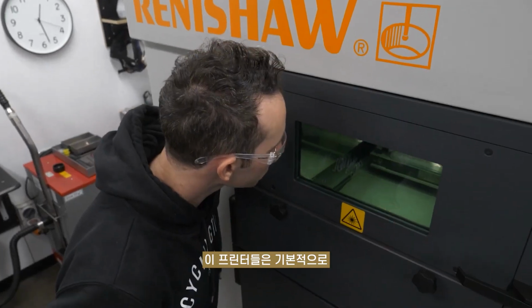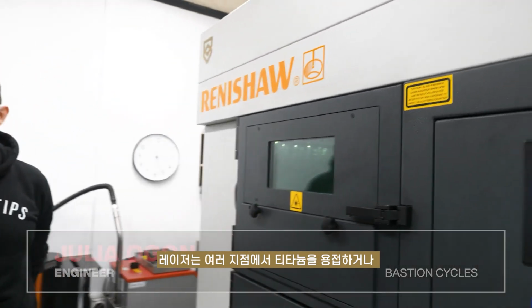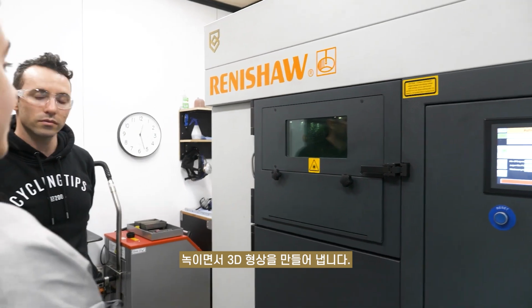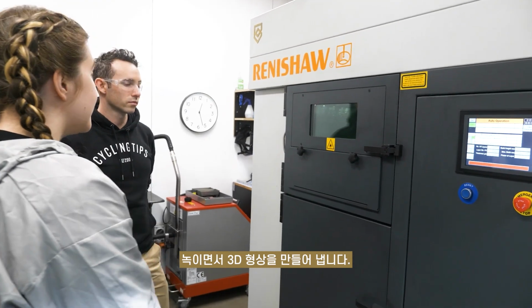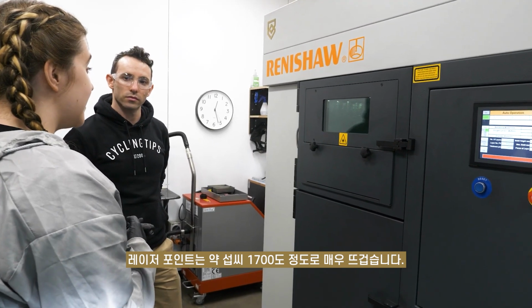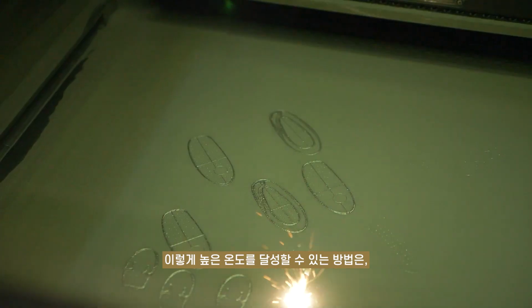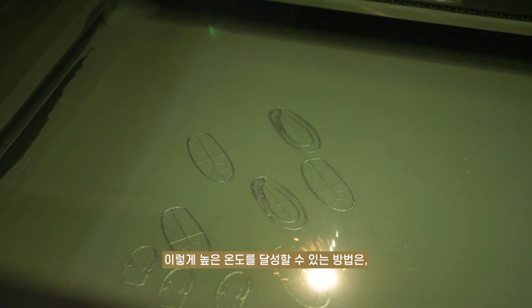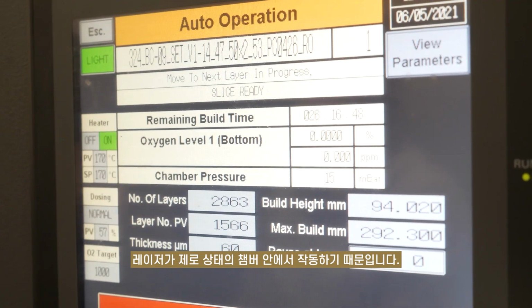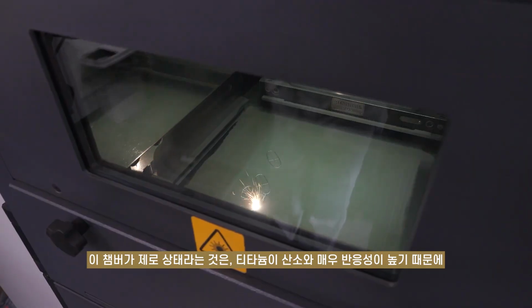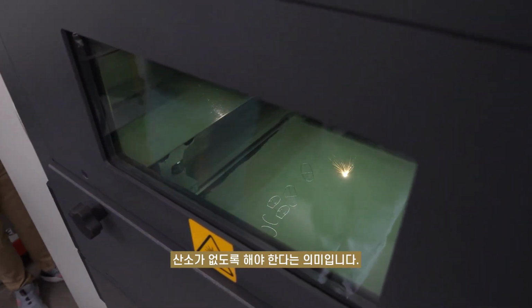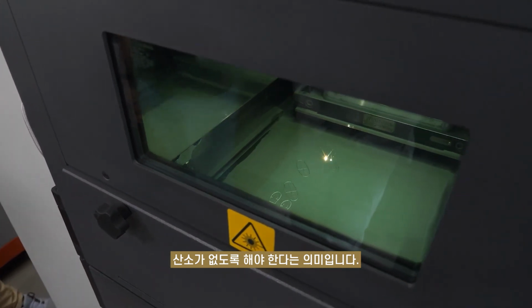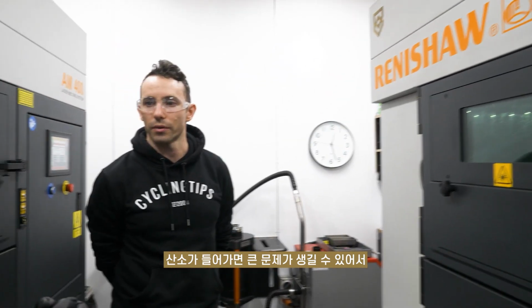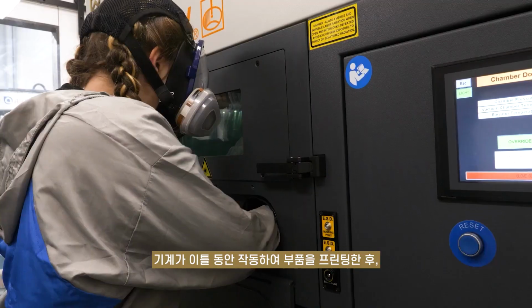So these printers essentially run off a really strong laser. The laser essentially in very minute points is welding or melting the titanium powder, and in the end creates a 3D piece for us. The laser point is at about 1700 degrees Celsius, so it's really, really hot, and the way we're able to achieve it being that hot is having it in a chamber that is zero oxygen. So there's no oxygen in there. It's filled with argon because the titanium powder is quite reactive to oxygen. So if there was oxygen in there, it would just be a fire pit, so it wouldn't work at all. So very important to make sure that the chamber has no oxygen in it, essentially.